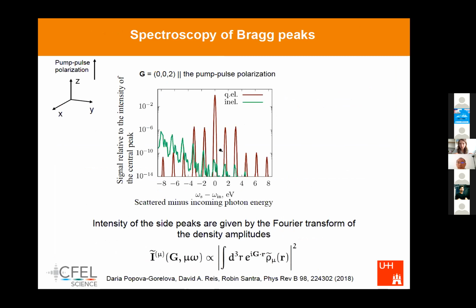And here I'm going to show you the result and what we can learn from this X-ray optical wave mixing experiment. So what we propose is to consider Bragg diffraction from this laser-dressed system. Magnesium oxide is very well known to have several bright Bragg peaks, and one of these Bragg peaks is at this scattering vector G, 002.